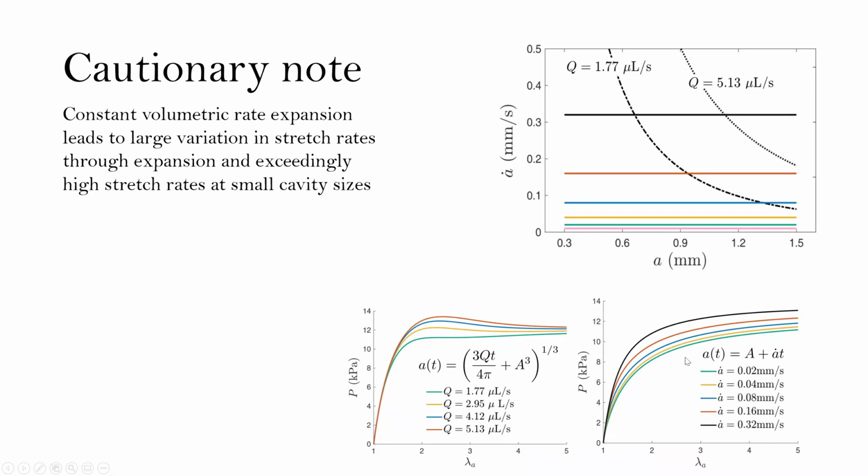And you can see that though the material is clearly viscoelastic, and we are able to clearly see that when we use this loading protocol, if you use the constant volume expansion rate, the response almost looks quasi-static. And this kind of falsely leads to the conclusion that, if you just did the experiment using this, you would think, oh, these are small volume flow rates and we are seeing repeatable overlapping pressure curves. So you'd assume that it's quasi-static and you try to fit this to get a modulus,